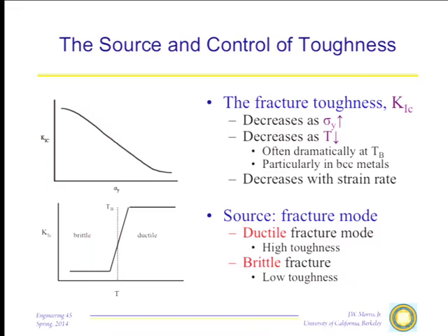The thing that really affects toughness, however, is the fracture mode. I'll do mechanisms next time, but just real quickly, you can fracture a material in microscopic modes that are ductile, in the sense that they involve a lot of plastic deformation, or brittle, in the sense that they involve almost no plastic deformation. If you have to deform the material significantly to propagate a crack, you're going to have high fracture toughness. If you don't have to deform the material significantly, if it's brittle, you get a low fracture toughness.